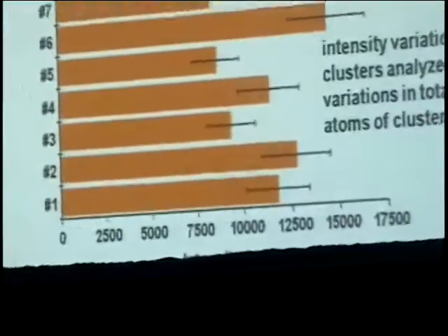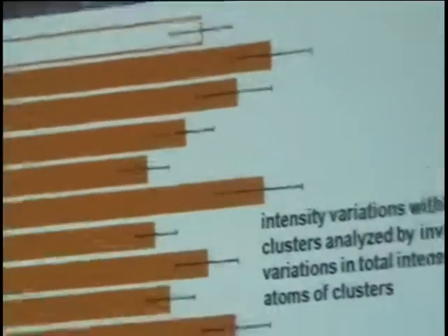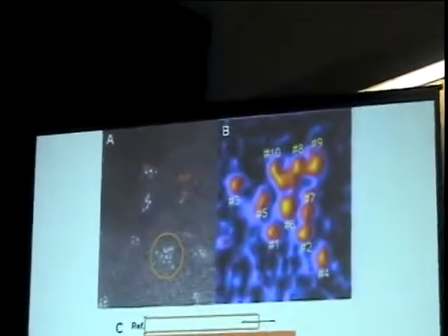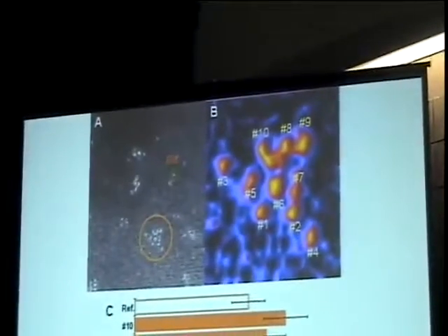And then she did statistics on all of this, and again, I won't go into the detail. She subtracts off the effect of the MgO support, which is variable from place to place, uses isolated osmiums, which remain in the mixture after this synthesis as a kind of standard, and then does the intensity analysis on the basis of that as a reference.